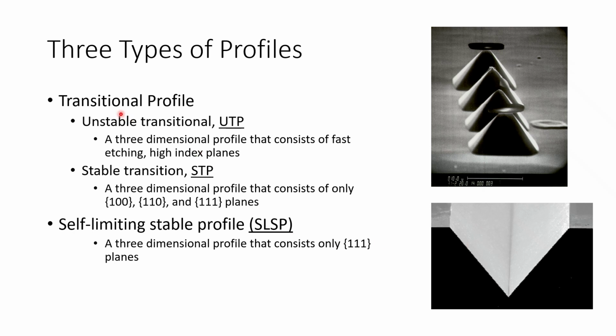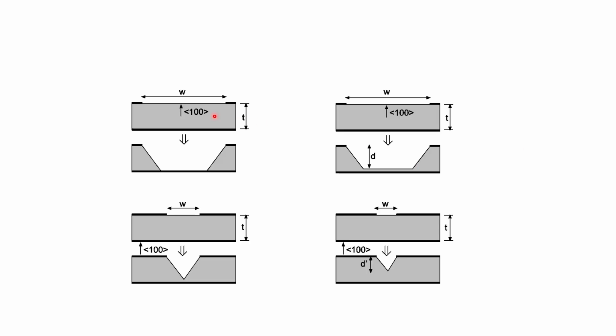You can have transitional profiles that are either unstable or stable. The unstable structures that are transitional change very rapidly. It's not a good situation if you want to have a high yield process. Depending on the combination of the width of the window and the depths, you can have cavities that look like this, or you can leave a little bit of silicon at the back. You can have a full inverted pyramid. If the window is very small, then the size of the cavity would be very small as well.